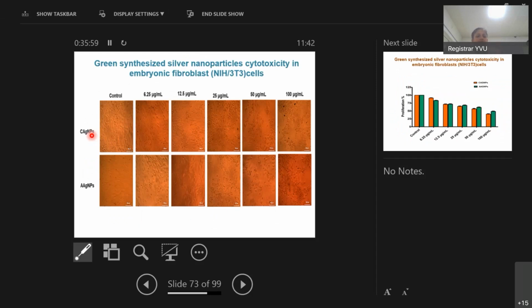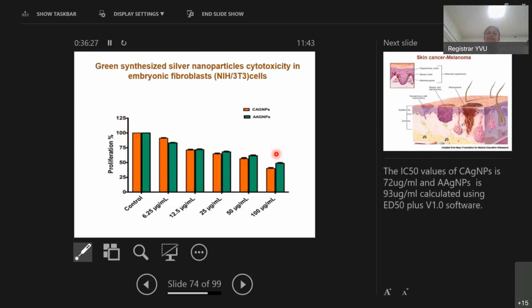The Catharanthus roseus and Azadirachta silver nanoparticles, from lower to higher concentrations, were treated on mouse embryonic fibroblast cells, NIH3T3, at concentrations from 6.25 micrograms to 100 micrograms per ml. The cytotoxicity was not observed at lower concentrations and showed less cytotoxicity at higher concentrations. This is the graphical representation of cytotoxicity observed in the embryonic fibroblast cell line. The IC50 values of CAgNPs is 72 micrograms and AAgNPs is 93 micrograms, calculated using ED50 plus software.